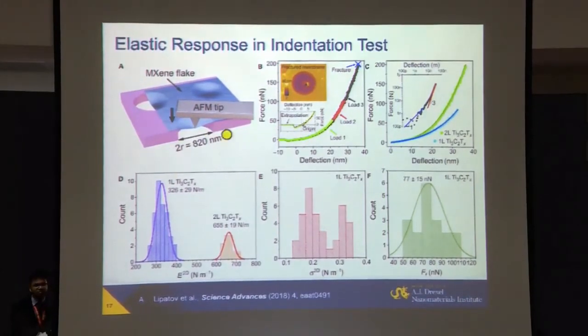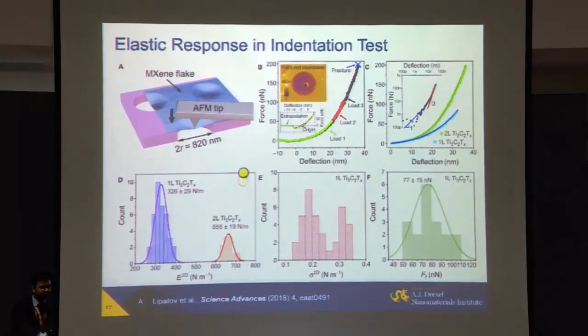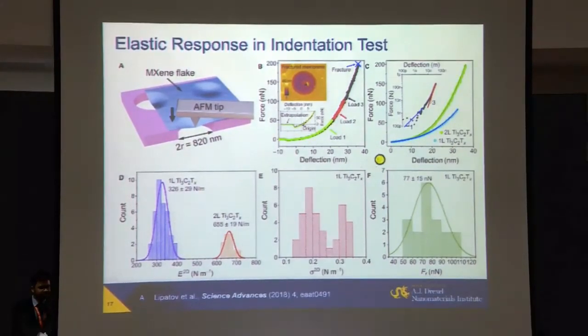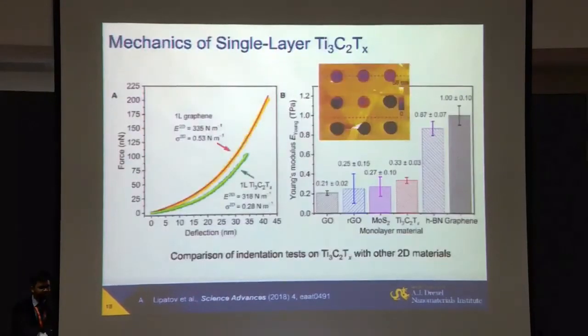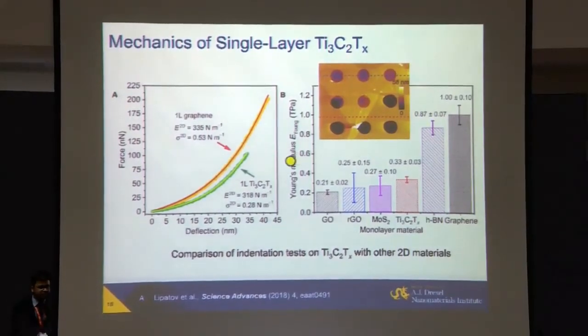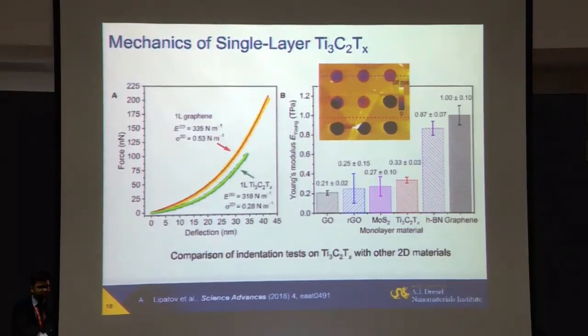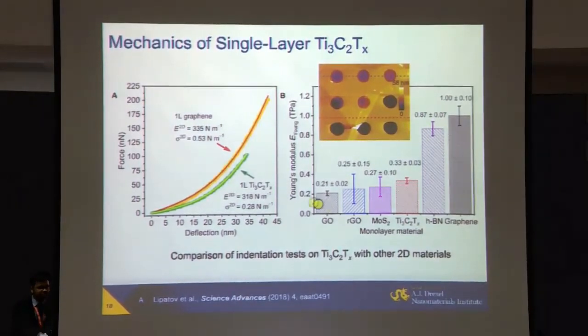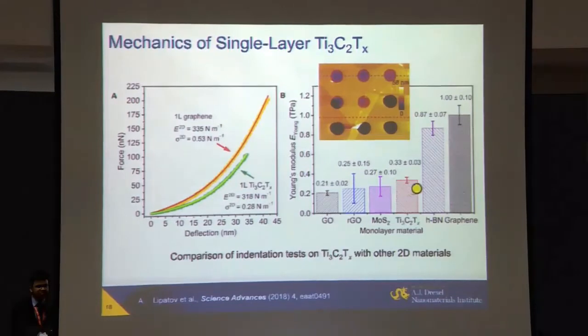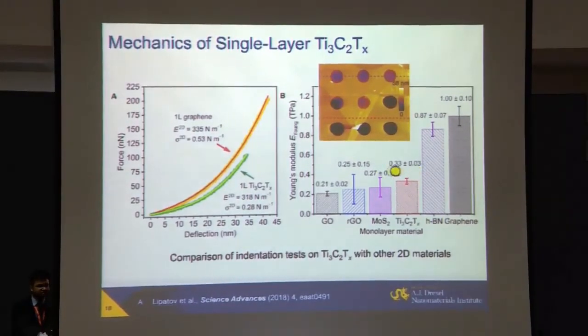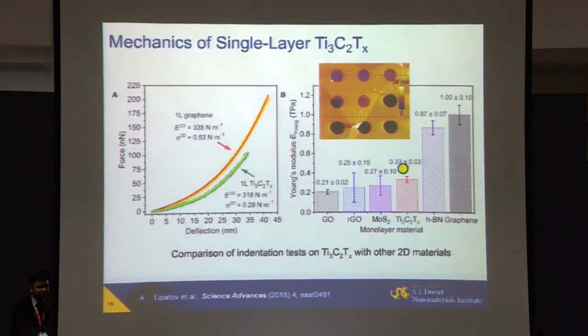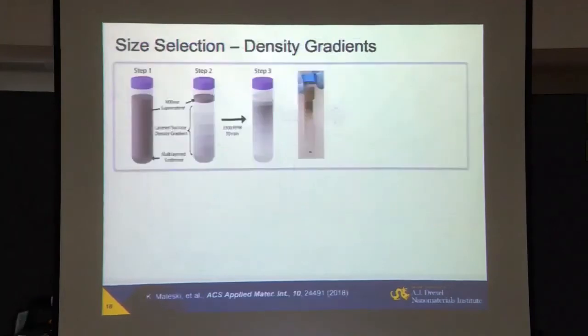So when you test, and this work was done with colleagues from the University of Nebraska-Lincoln, monolayers or double layers of MXene, you can find they're really very, very strong. And the ideal layer of boron nitride or graphene will actually show high modulus or high strengths, but those are ideals that are manually removed from a single crystal. If you take reduced graphene oxide, moly disulfide, the very first one, titanium 3 2 (Ti3C2), already has a high Young's modulus. We tested niobium 4C3 now, and it has about 430 gigapascal modulus and about 30 gigapascal strength. So those are very strong materials to add here.